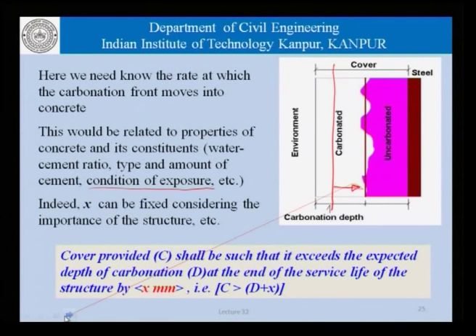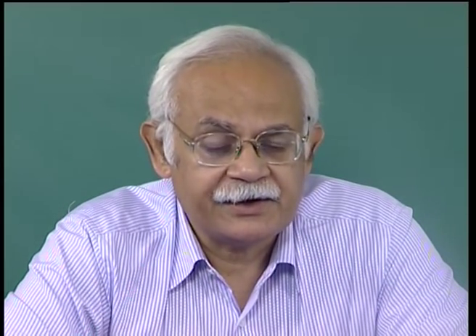And as far as the x is concerned, that is this additional depth, that is the additional uncarbonated concrete, this can be fixed considering the importance of the structure and other considerations. So, in a very important structure we may say that well x should be at least 15 millimeters, in other structures we may say 5 millimeters is acceptable, and so on. The principal thing is that if we keep on increasing the x, what we are really doing is prescribing higher and higher cover values, and that has its own implication in terms of the self weight of the structure, the economics, and so on.